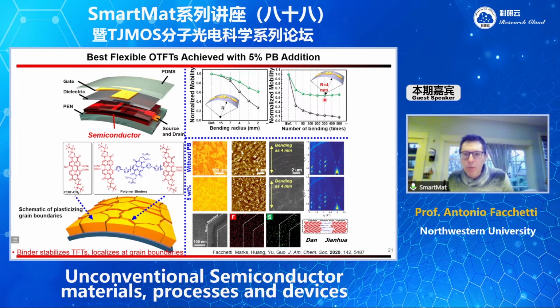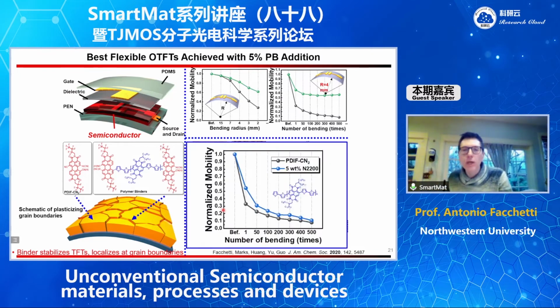And we indeed, using a different technique by mapping by elements, this is a mapping of a grain boundary. And in the grain boundaries, you see a lot of sulfur, and sulfur only belongs to the polymer. So indeed, this polymer likes to phase segregate at the grain boundaries. So it's a different strategy to plasticize them. And of course, if we add N2200 to this transistor at 5%, it doesn't plasticize the film, so the device degrades.